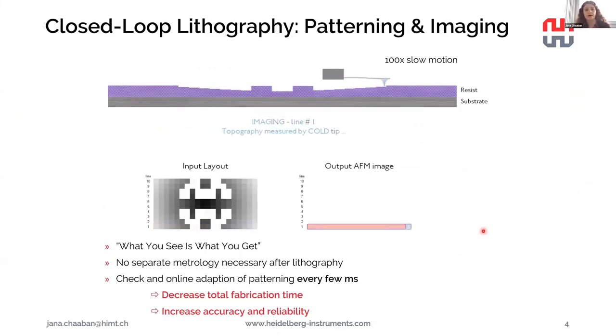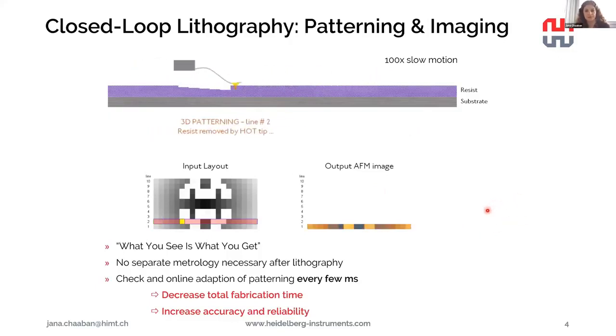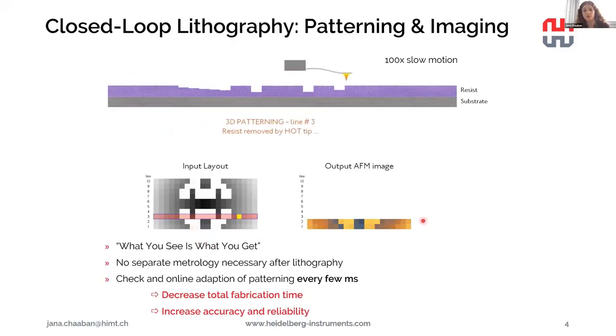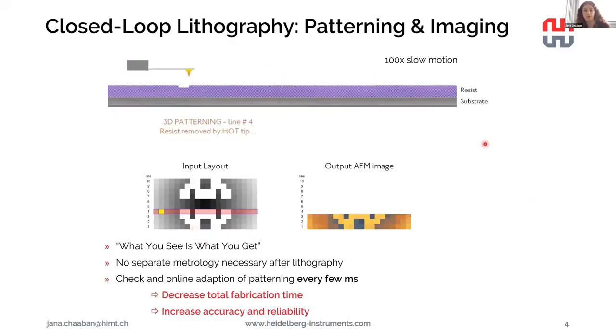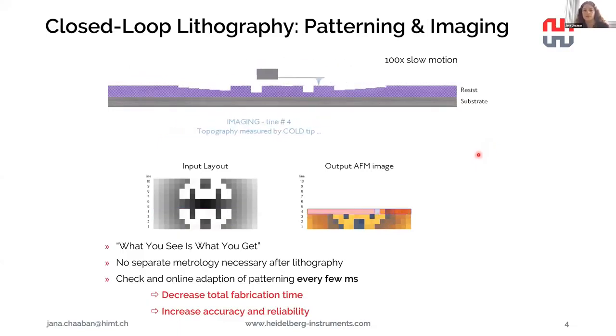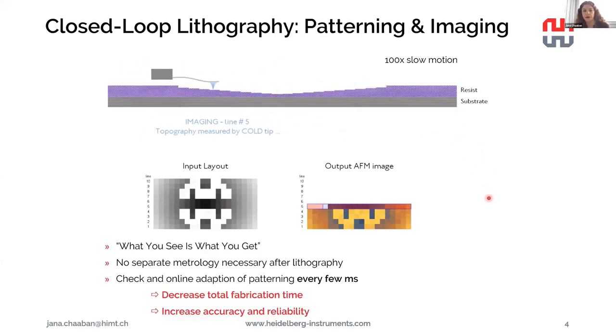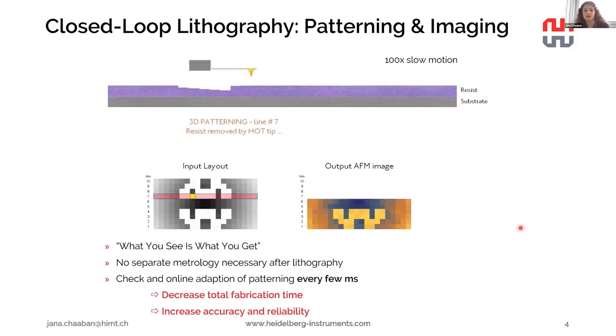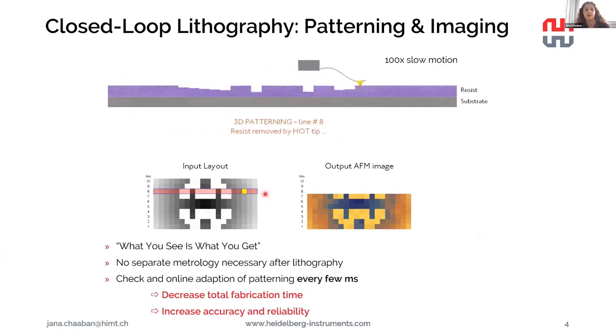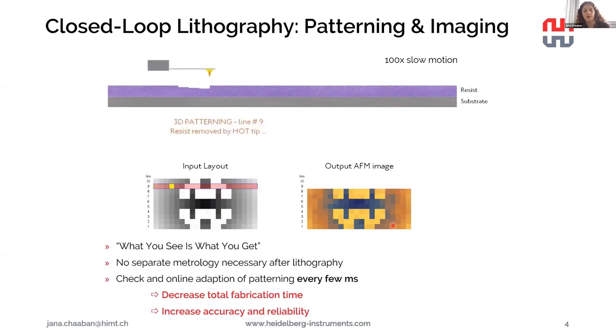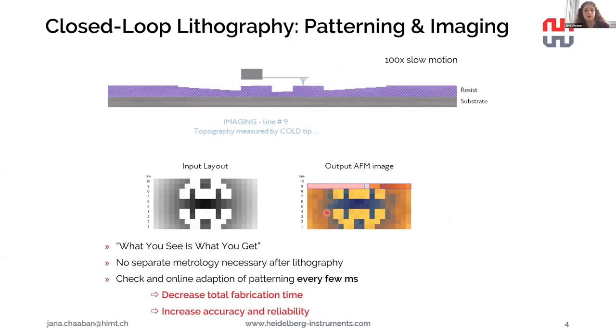Right. While actuating the microheater, the cantilever with a hot tip moves in one direction and removes the resist according to your input design. Then, switching off the tip heater, the tip goes back to room temperature in a matter of microseconds. Then it can be operated as a standard AFM to image the topography that was previously patterned. By doing so, our software compares the deviations from the intended design and feeds it back to the next line of the pattern. In this way, even the slightest design deviations of a single nanometer can be corrected and adapted into the next line to be patterned. This is a very powerful combination because we can see exactly what we're getting as a final design. It's really a what-you-see-is-what-you-get type of patterning.